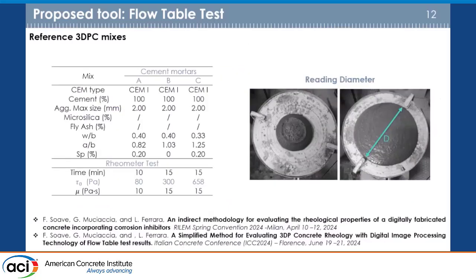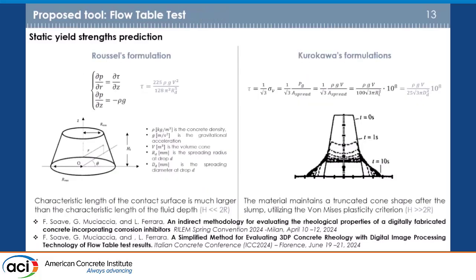3D printable mixes. So we started with 3 mixes that we found in the literature, and we ran the flow table test, identifying with the rheometer the yield stress and the viscosity parameters. Then, in order to process back the results of the flow table test, we used 2 analytical approaches that are available in the literature and were quite popular exactly for self-compacting concrete tools. The left one is the formulation proposed by Nicolas Roussel, which works pretty well for self-consolidating concrete, and the other one has been proposed by Kurokawa.